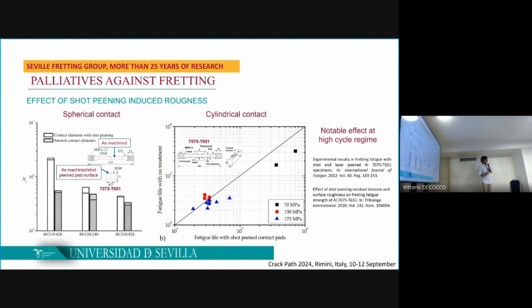In order to go deeper into the effect produced by the shot peening characteristic surface condition, we needed some special tests. In these tests, the fretting specimens were as-machined, but the contact pads were shot peened. Here, we can see that we did fretting tests in spherical contact and also in cylindrical contact. We observed that at the high cycle fatigue regime, the behavior was very good due to the surface roughness, in both cases, in spherical contact and also in cylindrical contact. But we also observed, in contrast, that at lower lives, the behavior is also clear. So with these tests, we observed the importance of the surface condition in fretting fatigue, not only residual stresses.